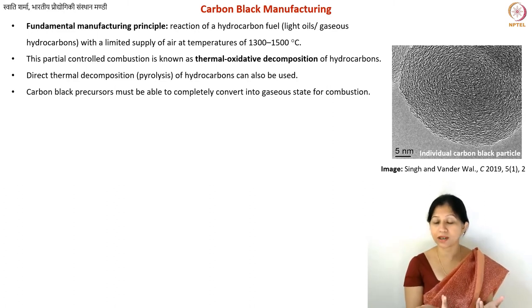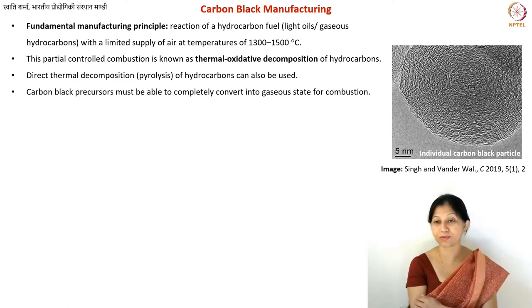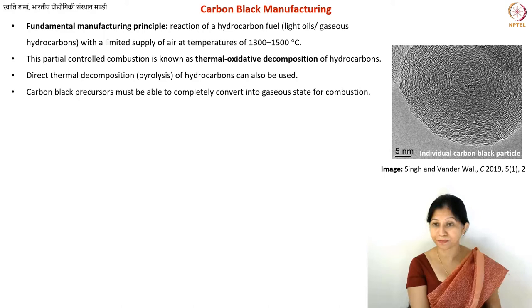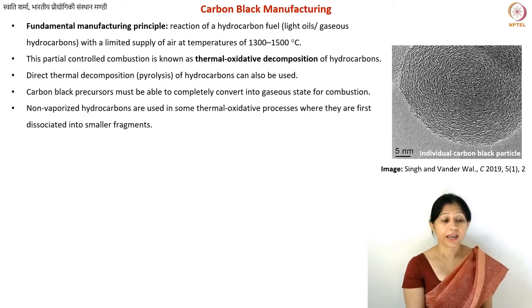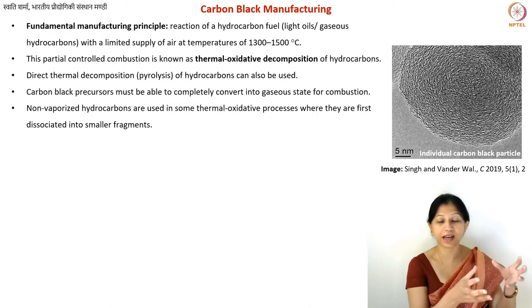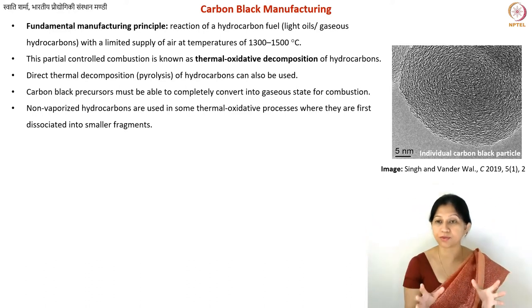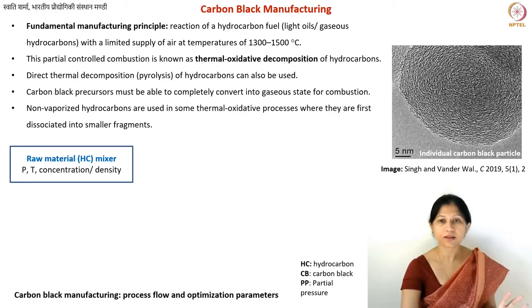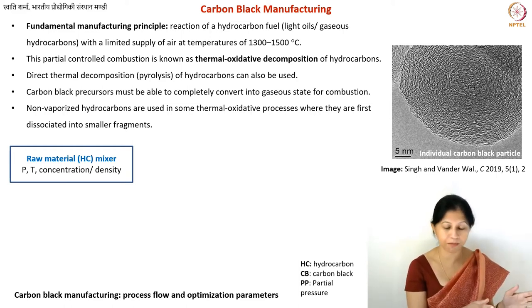As fuel, you can use hydrocarbon gases — methane or natural gas can also be your fuel. You can also use light hydrocarbons or light oils. If you are using light oils, you need to make sure they are disintegrated before going inside the reaction chamber where the actual combustion takes place. The idea is to have a very uniform distribution of your precursor inside your gaseous mixture.